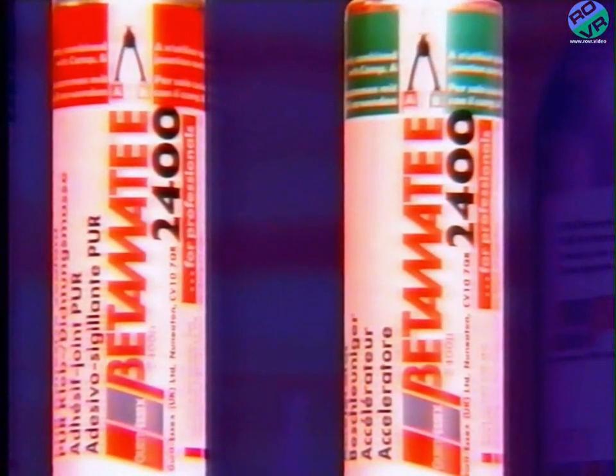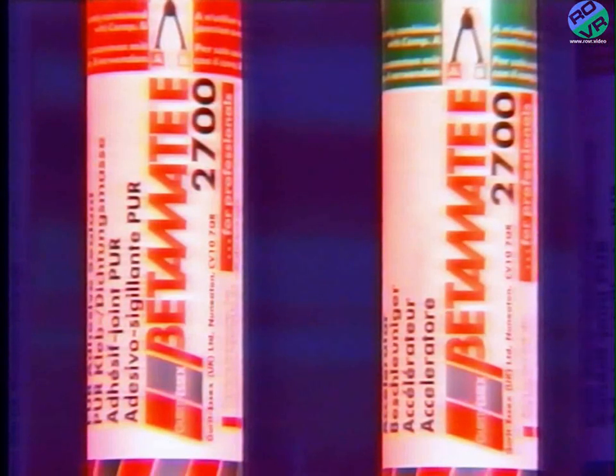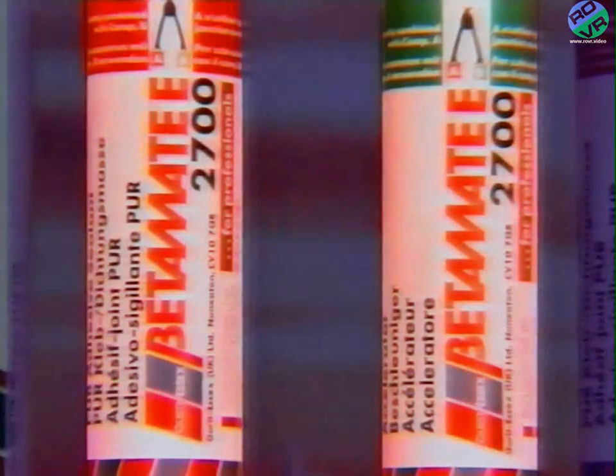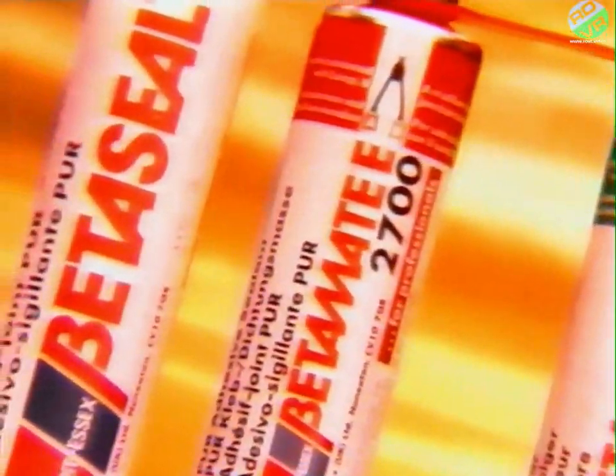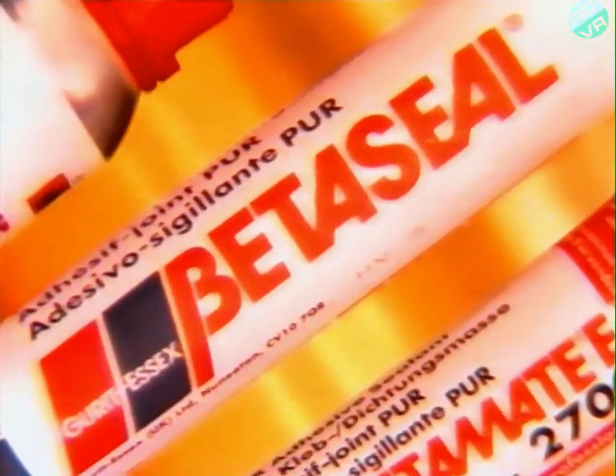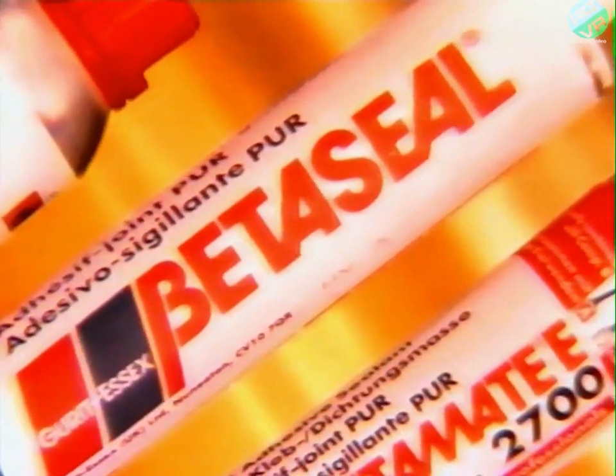Betamate E 2400, 10 minutes working time, the one you use most of the time. Next, Betamate E 2700, 30 minutes working time, the one for bigger jobs or awkward jobs where it takes some time to get the dams or trims into place. And BetaSeal, the one-pack air-curing sealant used by manufacturers and the one you use for large jobs such as trucks and buses. Remember, though, this one needs from 2 to 24 hours to achieve safe drive-away strength.